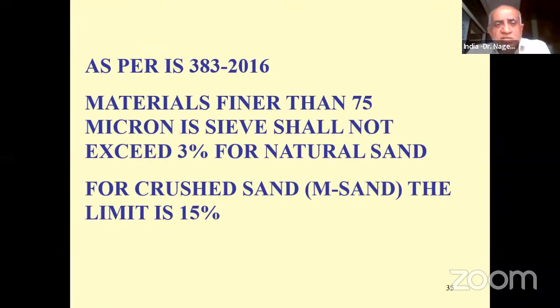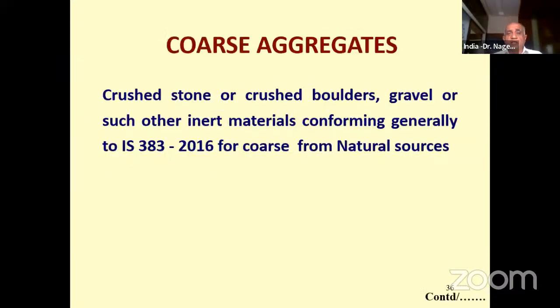IS 383 recommends a value of about 3% for natural river sand, and 15% for crushed stone sand, like M sand. M sand, I told you, can be BF sand or it can be copper slag sand. So for both crushed stone sand and M sand, the maximum limit is 15% for particles finer than 75 micron, whereas in the case of river sand, it shall not be more than 3%. As the silt content goes beyond 3%, the strength of the concrete gets reduced and the workability of the concrete also gets affected. So you should take care of this particular aspect.